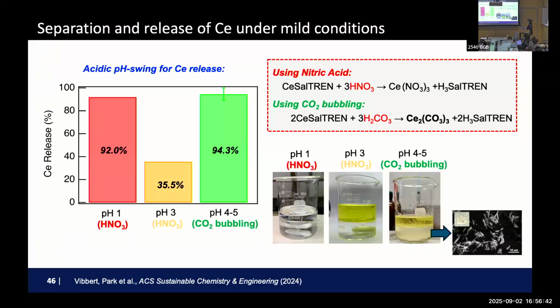If you do pH 3, we're trying to mimic the bubbling CO2 system. You can see that there's only a little, 40% or 35%, of metal comes out, right? Which is expected, right? But then when we bubble CO2, the pH only went down to 4 to 5. But we recovered 94%, more than the strong acid case. We were recovering most of the metal. So we're like, oh, confused. It was super exciting, but I was like, what's going on?